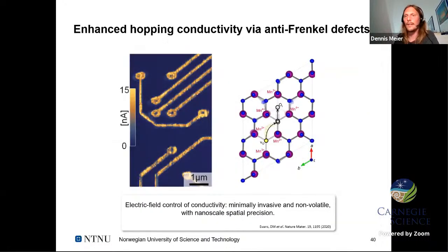What's happening now is these anti-Frenkel defects give new defect states, more carriers to the system, so we can really locally write conducting wires into our insulating material and thereby create conducting pathways, which in the best case we can also later on hopefully combine with the domain walls and then the 1D defects to get more complex features.